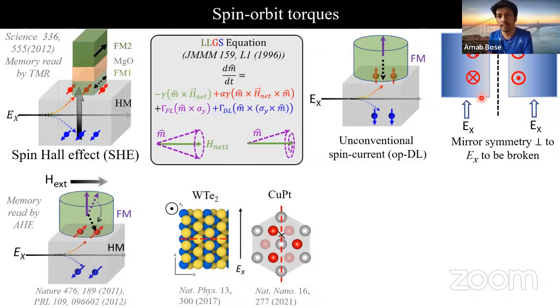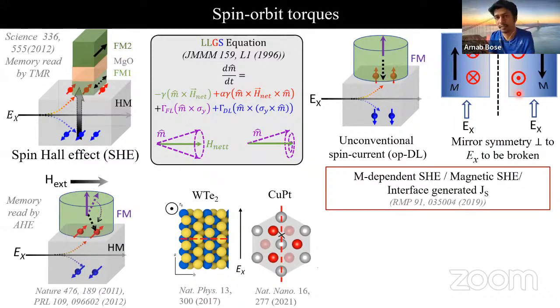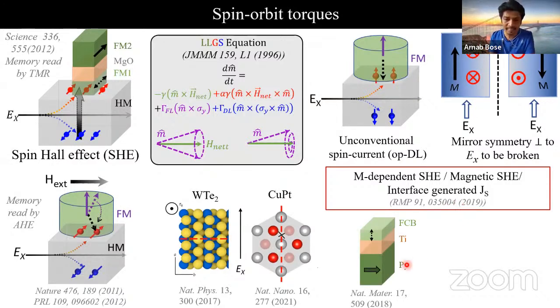But this is not the only way we can break the symmetry. If we have magnetic ordering, that also breaks the symmetry, and we can also obtain different types of unconventional torques. More details can be found in this review article. However, for now, I'll give you two instances. In this case, we have magnetic trilayers, out-of-plane iron cobalt boron and in-plane permalloy. We have a spacer in between.